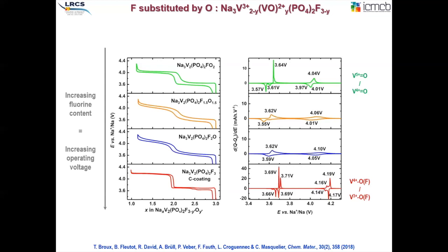As I mentioned, it is possible to prepare a whole series of compounds with different fluorine to oxygen ratio, here FO2. So that means that indeed the vanadium oxidation state changes quite a bit. And we might be careful not to actually say that we have vanadium 4+, but we have more of VO2+ units that are formed when we substitute fluorine by oxygen.